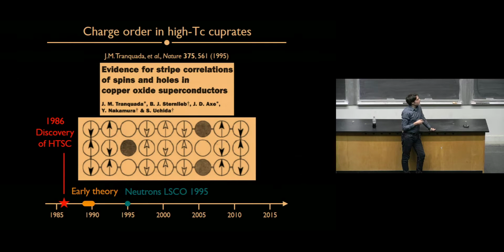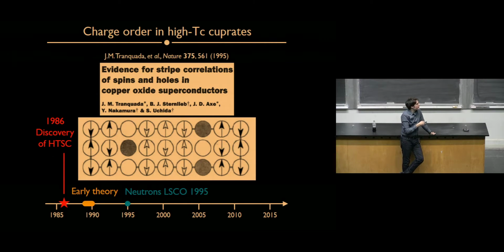They found this pattern where these black things are holes, and the rest are electrons. So there are basically one-dimensional rivers of charge, or stripes, that separate domains with antiferromagnetism. And these stripes are separated by four lattice parameters. So this is not quite a sinusoidal modulation of the charge density. It's more of a kind of phase separation between a region that has holes and a region that has electrons. And this was the first detection ever in the cuprates of these holes crystallizing into periodic patterns, these stripes.